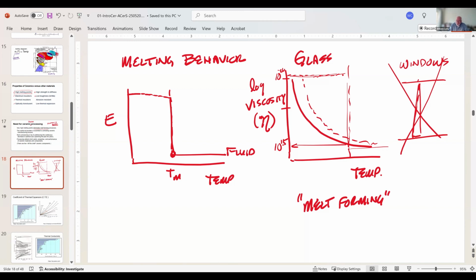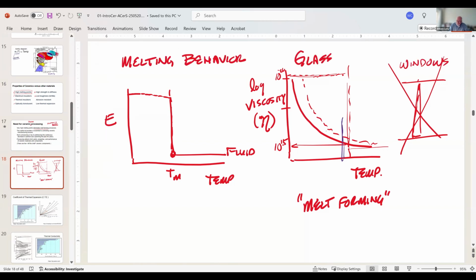And what they're doing is they're moving on this diagram, okay, in different places. So they are moving from this temperature to that temperature, this is what happens. They bring it out of the glass blowing chamber and it's here, and then they put it back in, and as they work it, the temperature goes down, viscosity goes up by several orders of magnitude, too viscous to work, they put it back in the furnace, and they keep cycling that an infinite number of times. So glass allows us to do melt forming, nothing else.